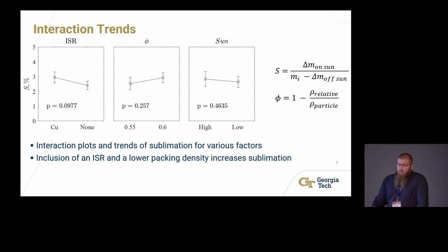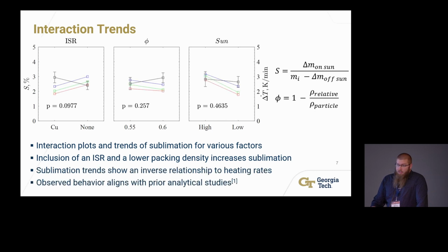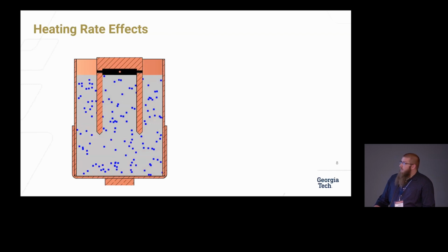But what we can do is look at the heating rates of these experiments in conjunction with the sublimations. And we see the actual inverse trend. So when there's a higher heating rate, we actually have less sublimation during these experiments, which is quite interesting. And we can also see the heating rates are somewhat uniform across. So this trend of sublimation rates decreasing with an increase of heating rates is something that has been shown in prior analytical studies.